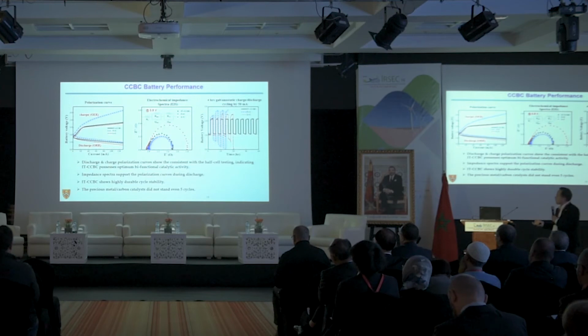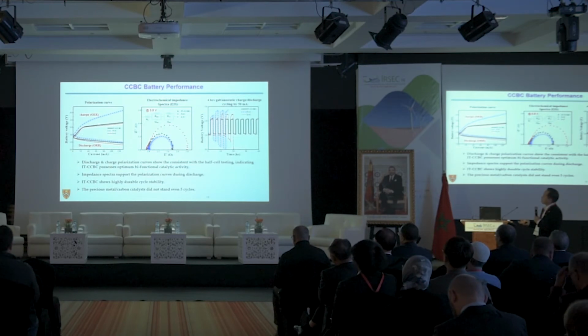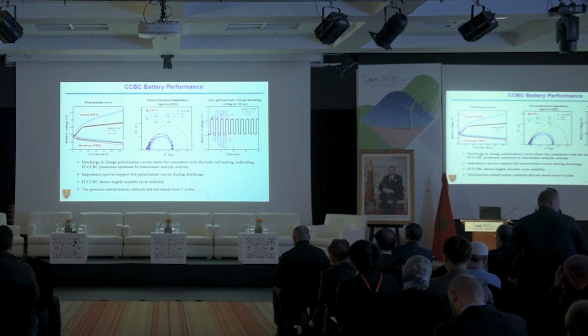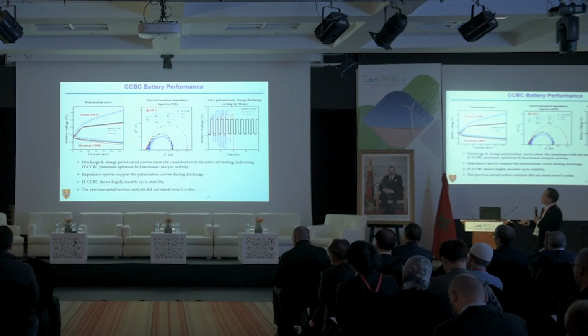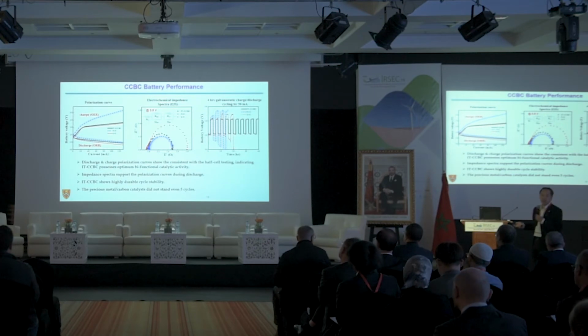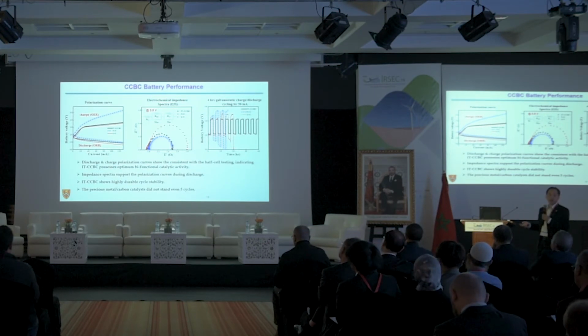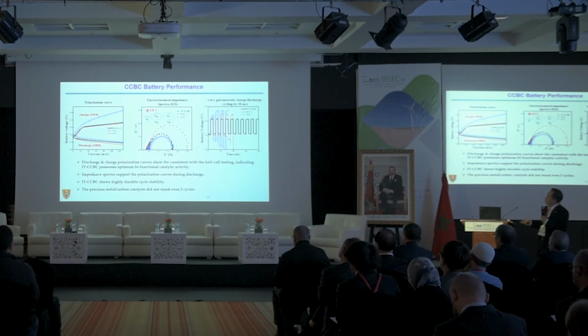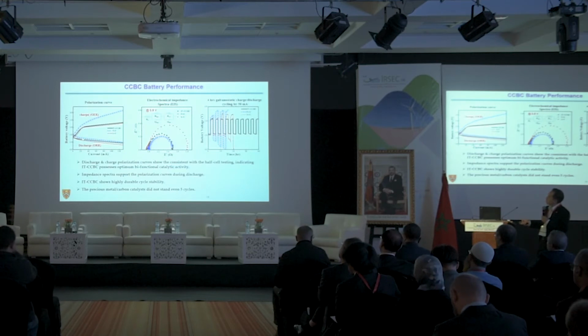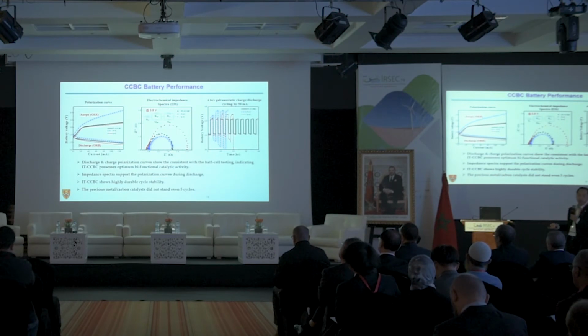So at the beginning we checked the discharging performance. If you compare the discharge, you see that our designed catalyst, we call it CCBC, the black one, shows similar discharge performance with the platinum. Because as you know, carbon-supported platinum is the best ORR discharge catalyst. For the charging, we also compare with the iridium. Iridium is proved to be a very good commercial OER, charge catalyst. So which means our designed catalyst has a similar discharge performance with platinum and a similar charging performance with iridium. So it has pretty good activity.